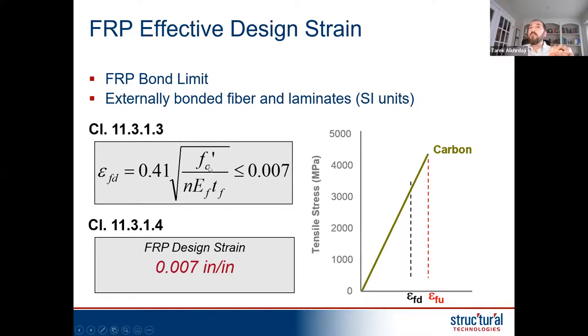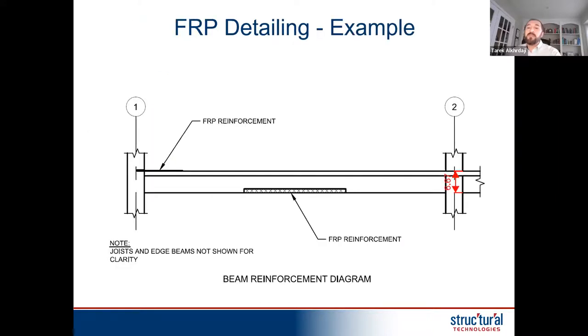And for the fabric, it's going to depend on the concrete strength because we saw it's a failure in the concrete, and also depend on the number of layers, the stiffness, the thickness, because the more I put, the lower this number is going to be sometimes. It will reduce. So take this strain, multiply it by the modulus, and that gives me the maximum stress I use in the design.